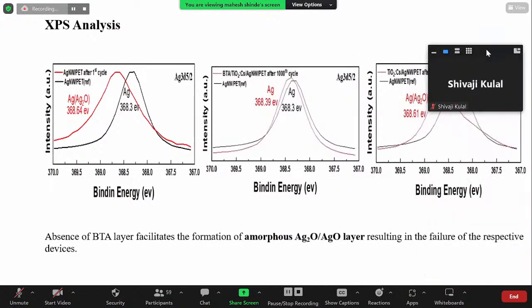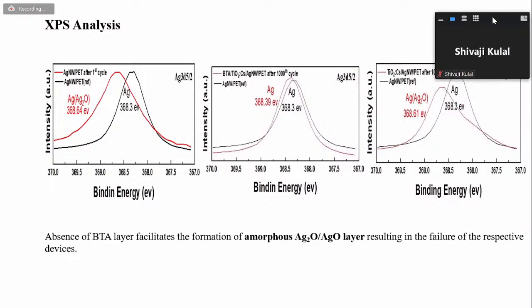After the XPS, you can also see that for the silver nanowire, after the first cycle, its XPS peak shifts to the left side, into the silver oxide region. And in the case of the TiO2 CS added, the XPS also shifts to the left side to the silver oxide state, which shows that there is oxidation and corrosion of the silver nanowire in the absence of benzotriazole.